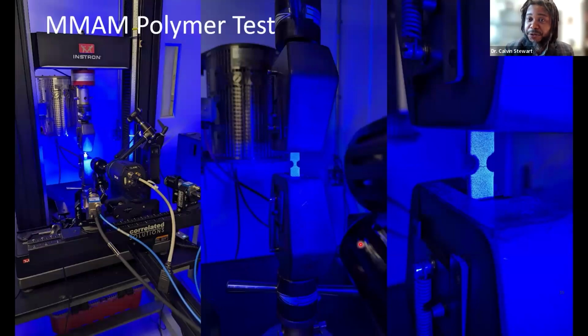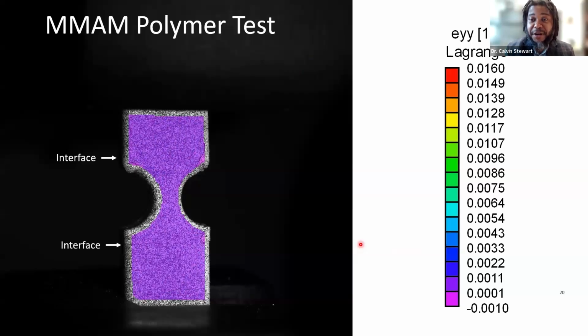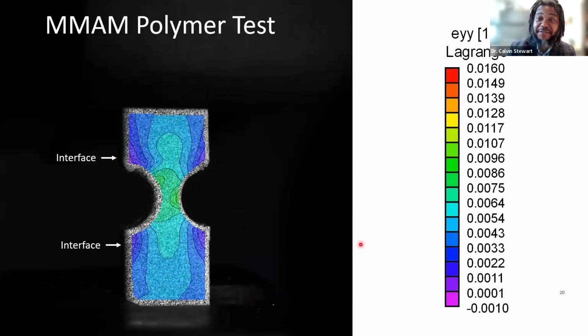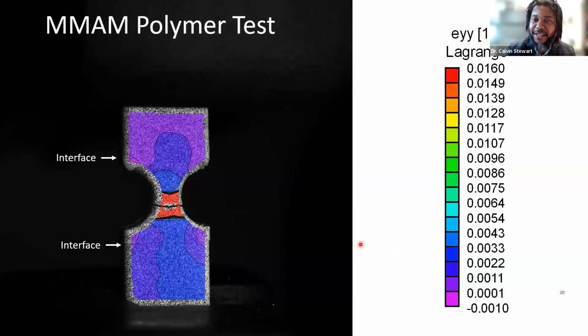From there, we moved to testing on our FDM prints of multi-filament type of tests. So testing samples of 2 different filaments that have a different stress strain response. And we found that our analytical and computational predictions match what we expected in the real world. But furthermore, we found that we had no stress concentrations at the interfaces, that if you select the right build parameters when you're printing your part at the interface, you can avoid any interfacial strains or mismatch.